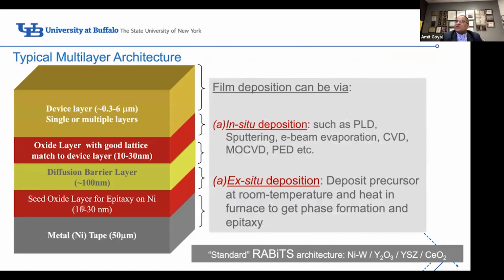We can make these depositions by what we call an in situ deposition process, like pulsed laser deposition, sputtering, e-beam, chemical vapor deposition, MOCVD, pulsed electron deposition, where the atoms, as deposited, achieve the right orientation. Or we can use what we call an ex situ deposition method, where we take the tape, dip it in a chemical solution, and then take it to high temperature, and that's when the atoms get aligned. Both of these processes work beautifully.